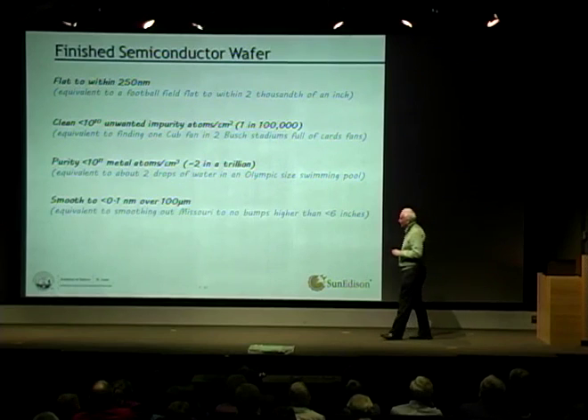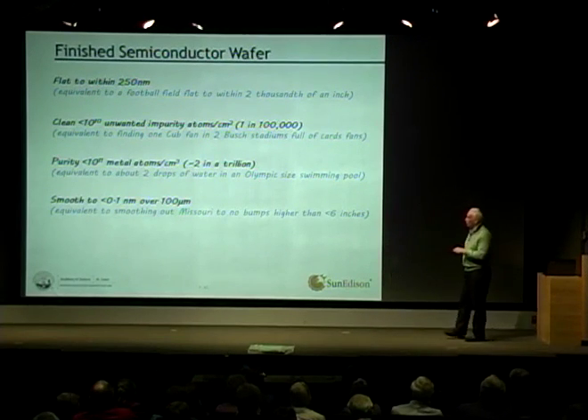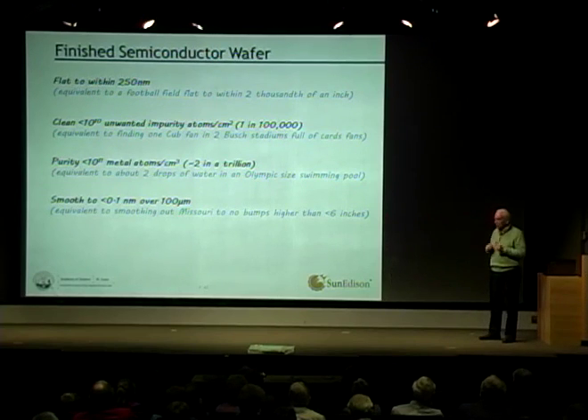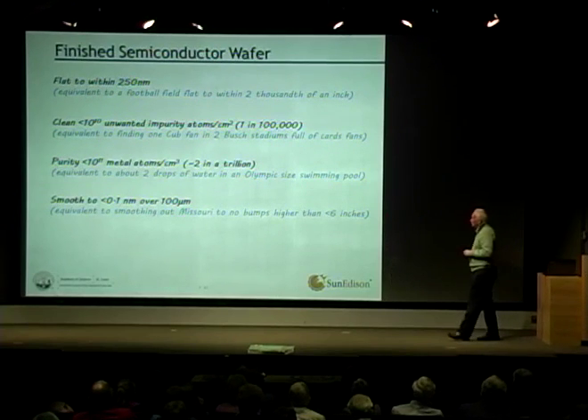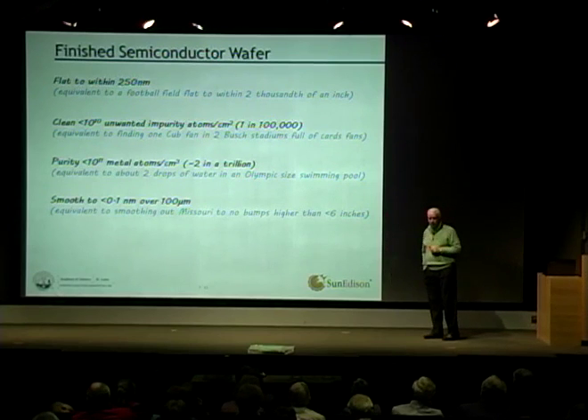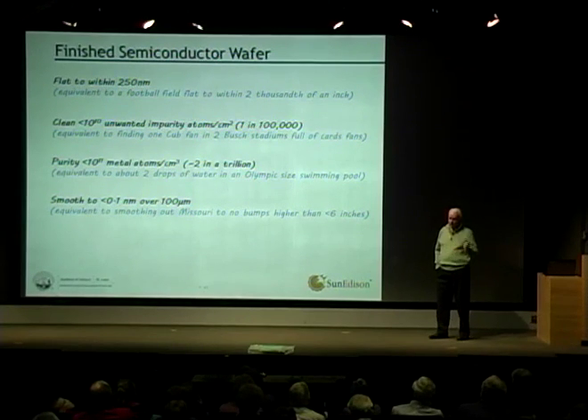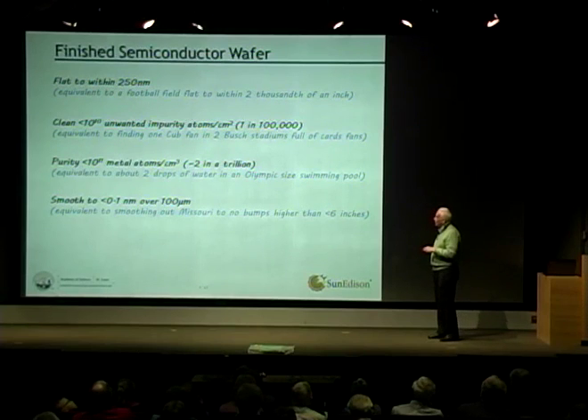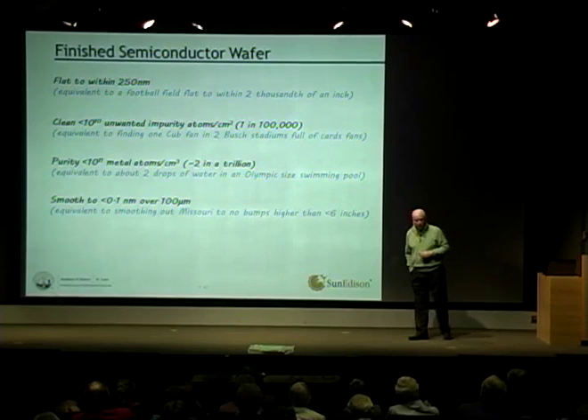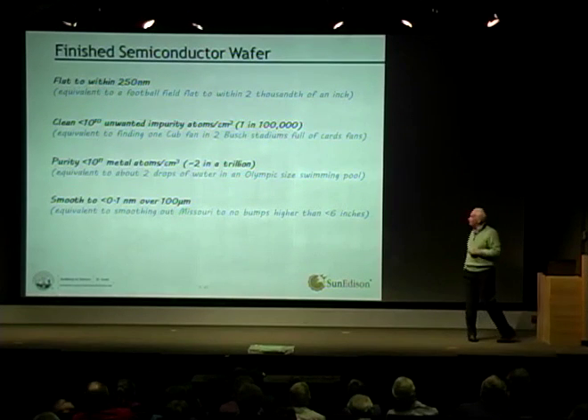I like this one, too. It's smooth. We get it down to 1 angstrom, so 0.1 nanometers over a 100 micron scale. And that's equivalent to smoothing out Missouri so there are no bumps higher than 6 inches. Now, of course, you can never do that, but it just gives you an idea if you start thinking about the scale of these things.